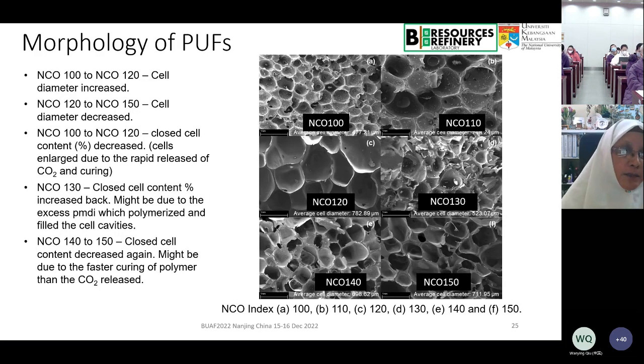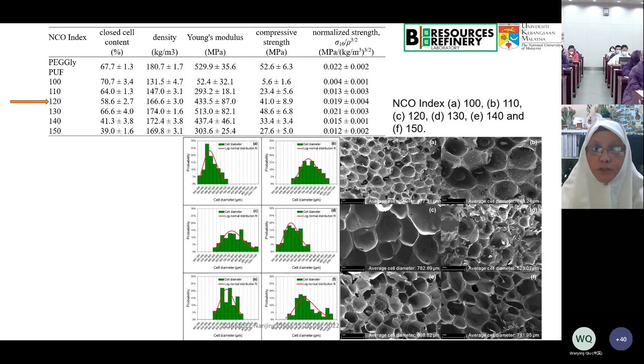For example, this is how the morphology of polyurethane foams looks like. You have lots of foam structure, the cell structure, and the cell structure increases as the amount of NCO is increased from 100 to 110 and 120, then it starts decreasing, and this is attributed back to the strength of that particular material. But again, as I told you, natural fiber is very difficult to control, because the lignin itself varies from one species to another, from one place to another, from the top to the bottom of the trunk, or even in the same fruit plant. The percentages of H, S, and G are totally different, even though the components are the same.